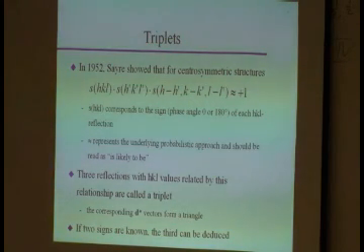Okay, this goes back quite a while. 1952, a guy called Sayre actually showed that if you have a centrosymmetric structure, so once again we'll talk about the simplest case, if you have 3 reflections with indices that are related as HKL, H'K'L', and the third one, each of the indices is the difference between the numbers of the other 2.